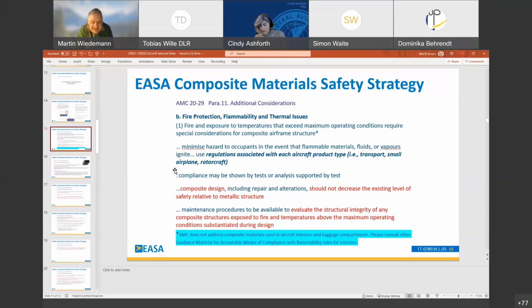I'm trying to think on the spot here, Martin, what I need to ask Simon. But I suppose, Simon, that thinking ahead, the fiber placement process itself on such a complicated double curvature structure will, depending on how the programming is assigned for each layer, end up requiring sectorization. And you will end up with voids and gaps, and depending on your philosophy, you might have gaps or overlaps, etc. But it springs to mind with us, and particularly in Belfast, that we have limited knowledge in terms of certification of fiber placement products.